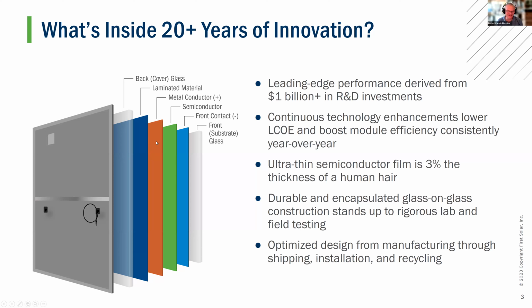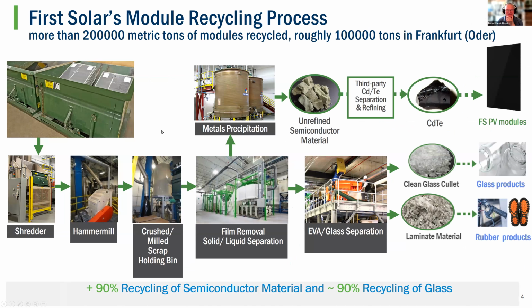We need a back contact, obviously, and then we have the lamination material, which has been EVA in the beginning, but I think now we are using polyolefin, which is a little bit simpler for recycling, and especially it makes the whole chemistry of the module more stable, so we can have a better lifetime. So that leads us to our recycling process.